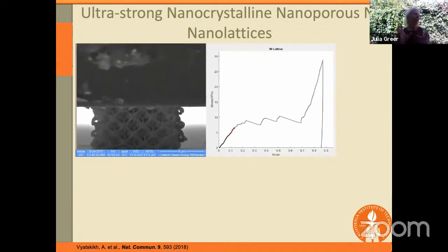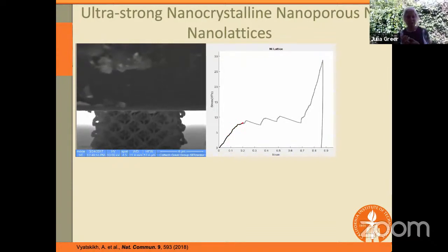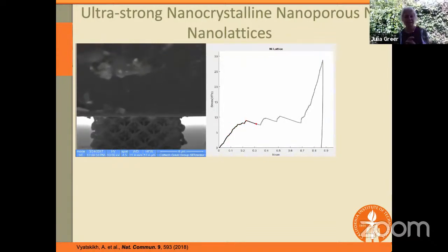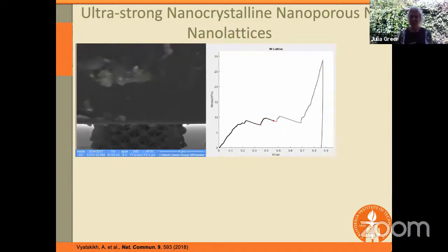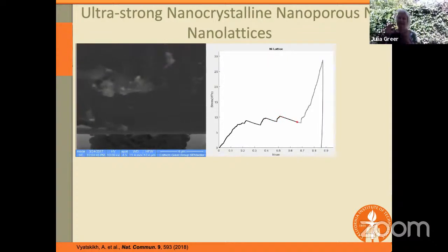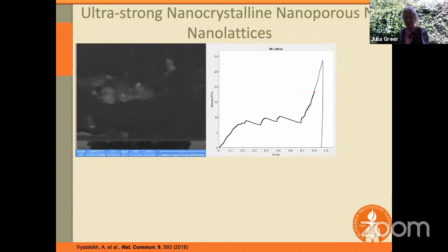Now I'd like to point out again, it's nanocrystalline, it's nanoporous, and it's not exactly pure. So according to any metallurgist, this is a terrible material. It's a very low quality material. It has impurities, it has pores, so it should be relatively weak. It shouldn't have a good strength, right? Now, as we're compressing this material, you can see that it behaves just like any cellular solid would, but it doesn't recover. Again, something that we would expect for a metal.